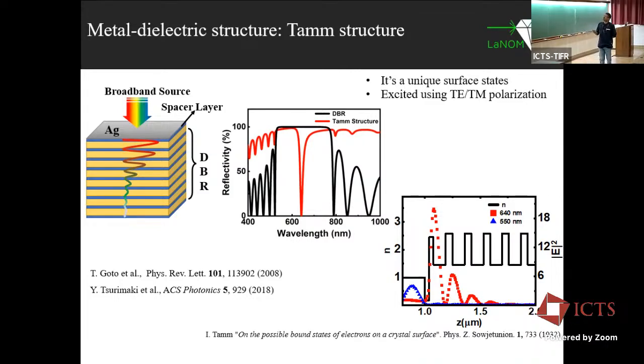So we came up with this idea where we have a metal dielectric structure. Basically it's a DBR, a distributed Bragg reflector, with low and high index layers. Then you have a silver layer on top of that. In the literature, this is known as Tamm structures. If you don't have a silver layer, you calculate the reflectivity using a simple transfer matrix method and you have a 1D photonic band gap. The moment you place a silver layer on top, you get a cavity mode at 640 nanometer.